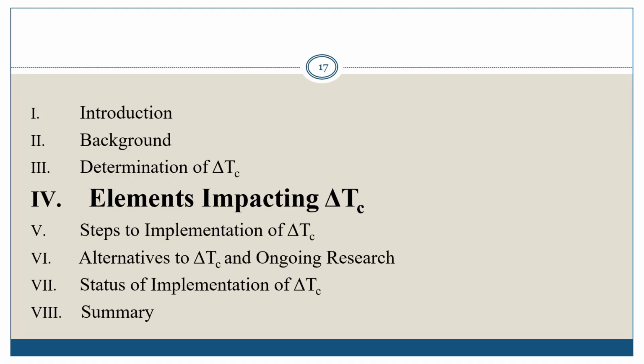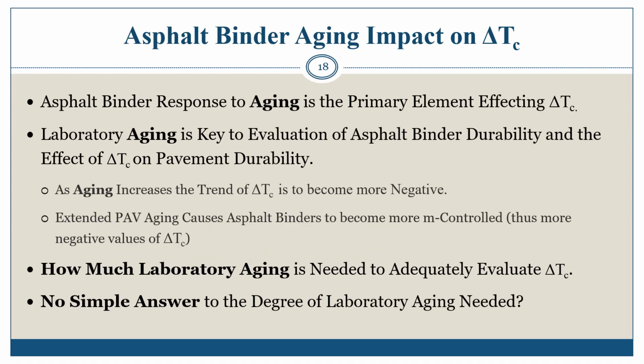What are some elements that impact delta Tc? An asphalt binder's response to aging is the primary element affecting delta Tc. As asphalt binder ages, the delta Tc differential generally becomes greater and more negative, indicating what is believed to be loss of relaxation properties as the asphalt binder becomes more m-value controlled. The effects of aging on the delta Tc parameter calls to question what degree of laboratory aging is necessary to adequately evaluate delta Tc as it relates to field performance. There's not a simple answer to this question. Binders will need to be aged relative to the degree of distress with aging in the field.